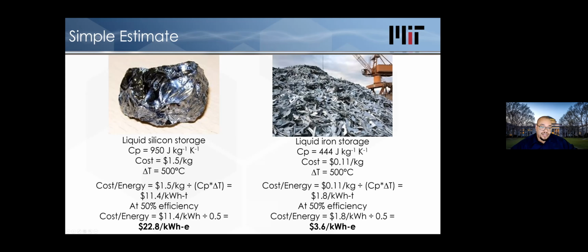Silicon, the heat capacity is 950 joules per kilogram per Kelvin. Cost of silicon, this is not semiconductor grade silicon, but metallurgical grade silicon, is about $1.50 a kilogram. Silicon is one of the most abundant elements on the planet. It's essentially the other part of sand. So sand is basically silicon and oxygen. If you remove the oxygen, you get the silicon back. And so we have lots of that on the surface of the earth. It can be very cheap.